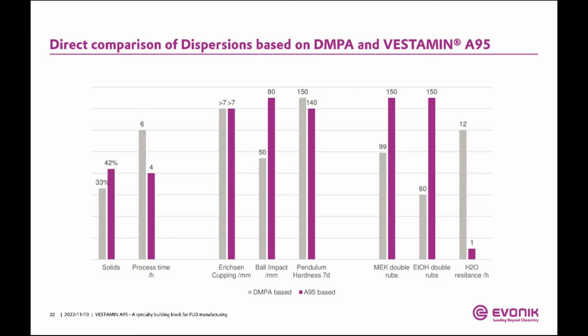So roughly 100 to 150 or 60 to 150. But also here, I would not overestimate this advantage. This can be compensated if you tune other parts of the formulation. So I would say, again, they are pretty close together, DMPA and A95.